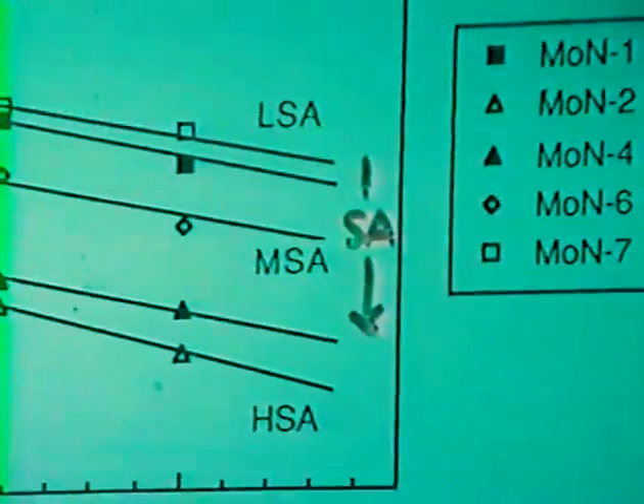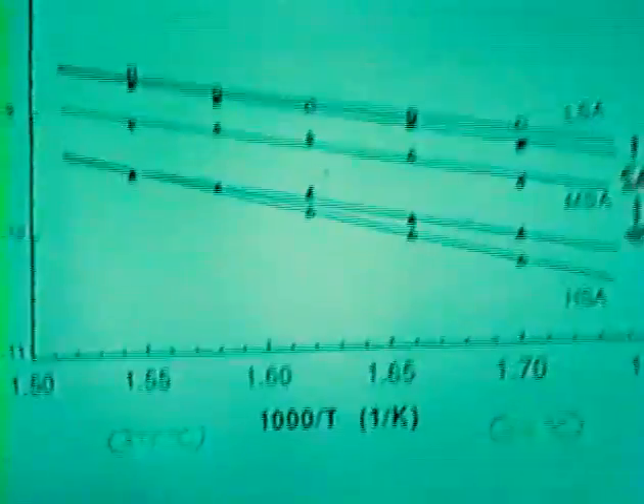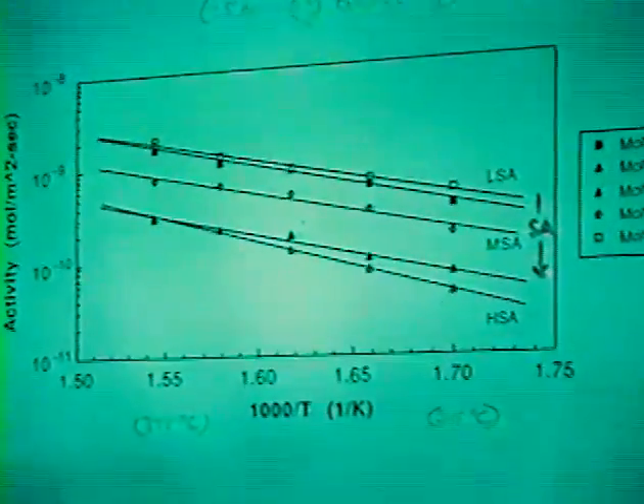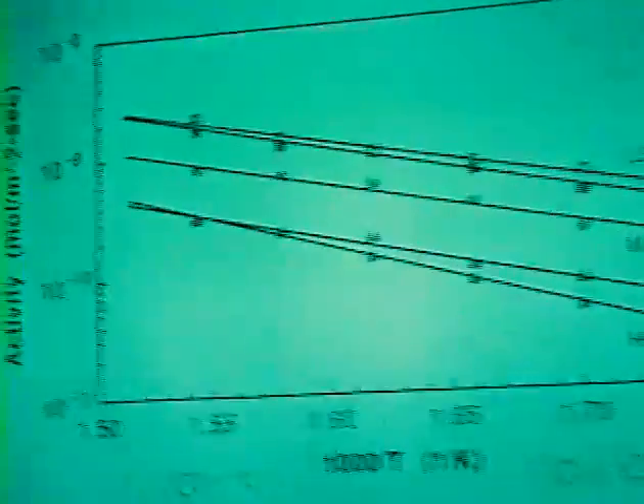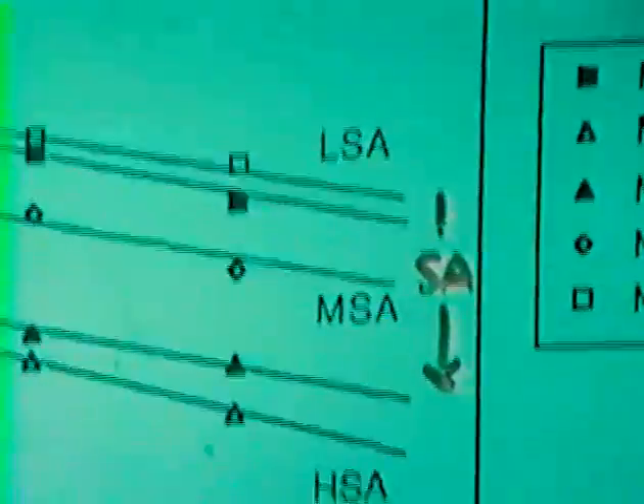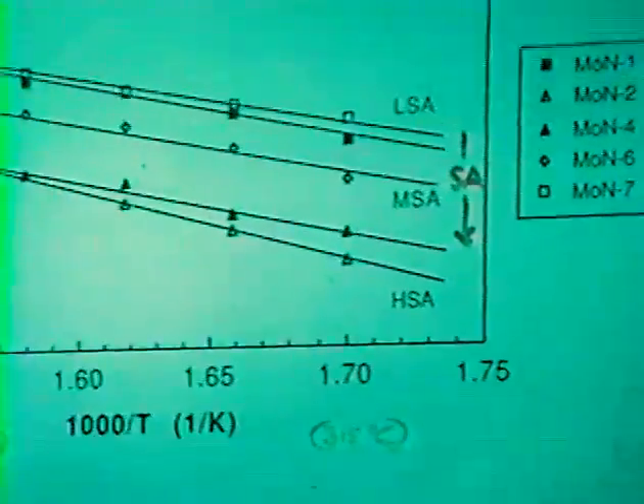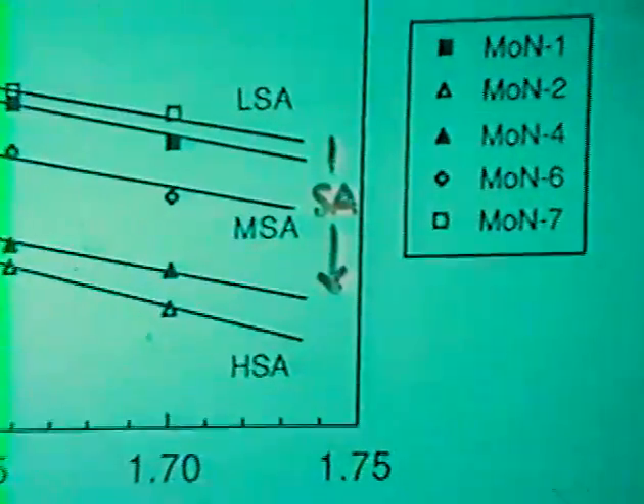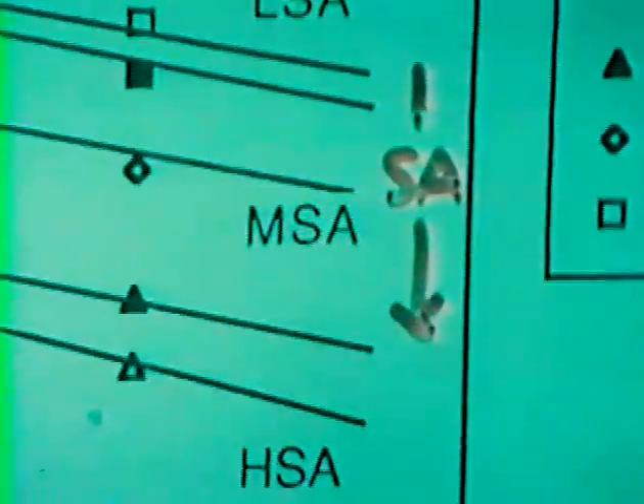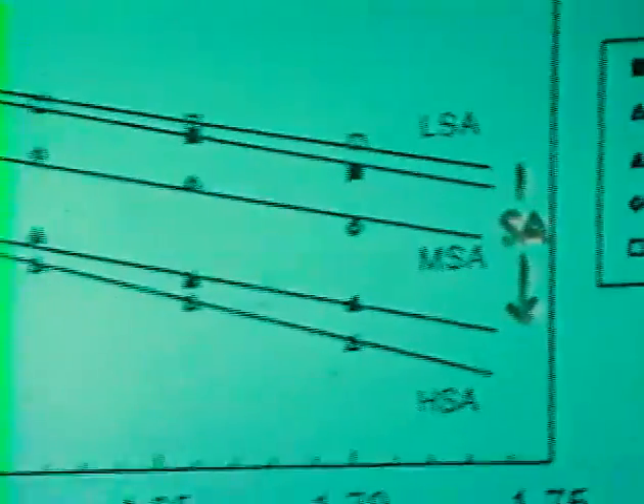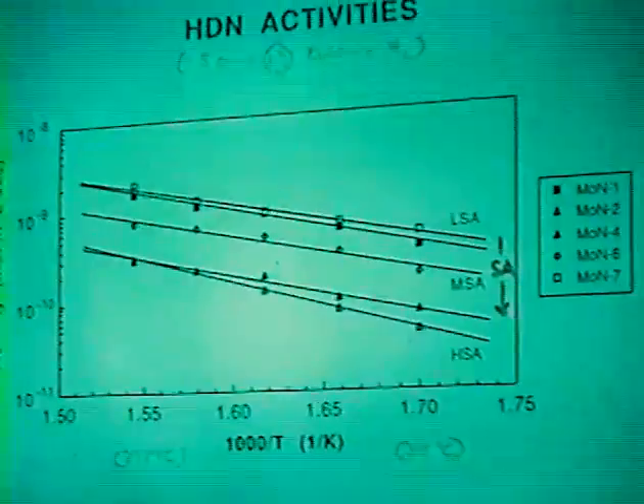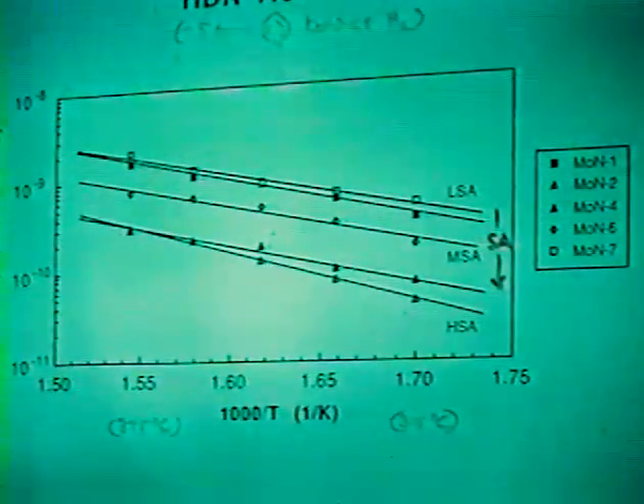In terms of catalytic properties, we find that they're very active for hydrodenitrogenation. They're competitively active with most commercial HDN, HDS catalysts, which is very intriguing. This talk will not deal with any of those types of comparisons. We will only compare the structural properties of molybdenum nitrides with their catalytic properties. What we notice is that on a surface area basis, the activity appears to decrease with increasing surface area. This is a classic example of structural sensitivity.